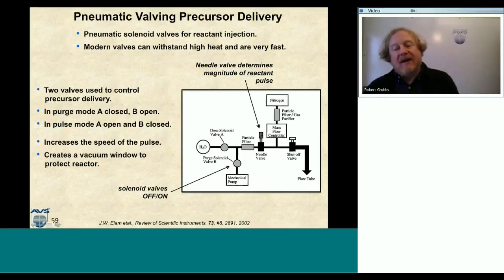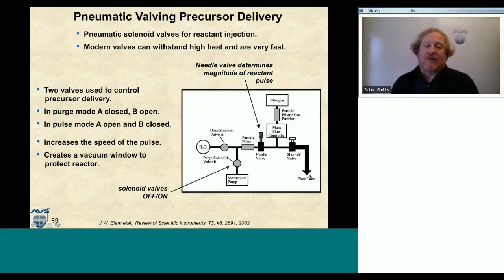Here we have, this is from a design by Jeff Elam. We can see here we have a water precursor and we have our flow tube, and we have a nitrogen source. So nitrogen comes through here and typically just flows through the ALD reactor tube. And back here in the reactor delivery manifold, I've got two solenoid valves, A and B. And I've got a mechanical pump attached to the B. And I've got this needle valve right here.